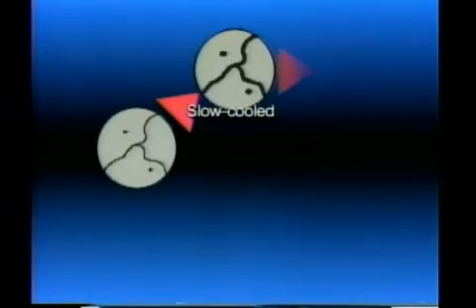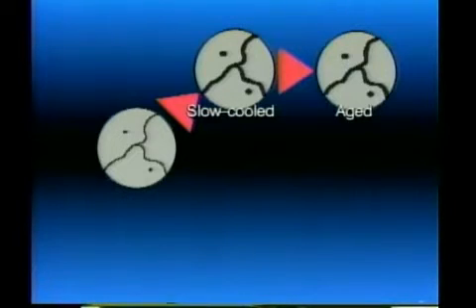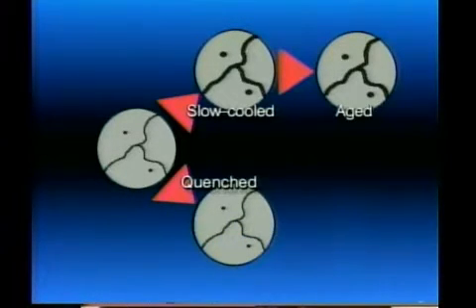A schematic illustration of the microstructural changes that occur during the slow cooling and quenching processes is shown here. At the solution heat treating temperature, all of the alloying elements are dissolved in the aluminum structure. When viewed under a microscope, the only structure visible is a matrix with fine grain boundaries and a few small undissolved particles. When the material is slow cooled, the atoms diffuse to the grain boundaries and to other defect areas in the structure. No further changes will be noted when this structure is aged. If the solution heat-treated part is quenched, however, the structure after quenching is similar to that before the quench, as the alloying elements have been frozen in place.